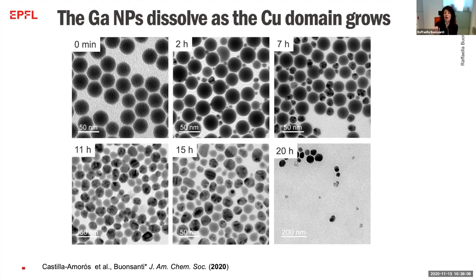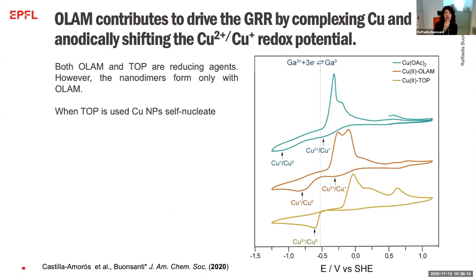And she indeed also found gallium ions in solution. So this behavior was consistent. But then what about the oleylamine? Well, here Laia ran some cyclic voltammetry on the complexes that form between the copper and these ligands. This is the copper acetate, and this is the copper amine complex. What the amine does is shift the first reduction of copper, from copper 2 plus to copper plus, toward more positive potential, and so it increases the driving force for the galvanic replacement reaction. It's not a reducing agent, because if we use a reducing agent like triethylphosphine, the copper just nucleates. So the role of the amine is to complex the copper and to change the driving force of the galvanic replacement reaction.